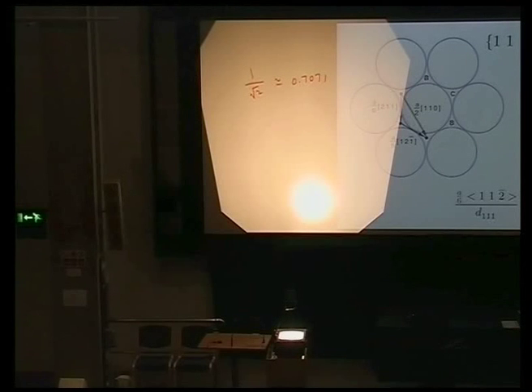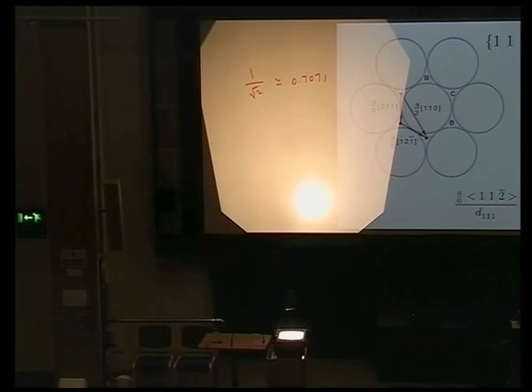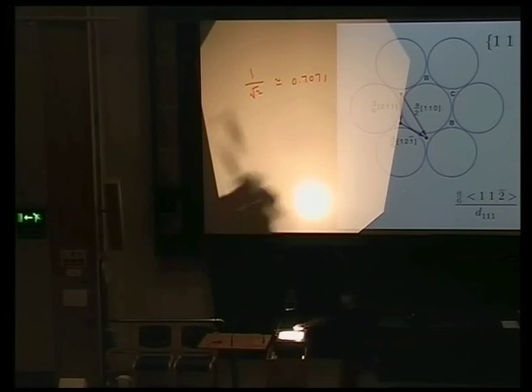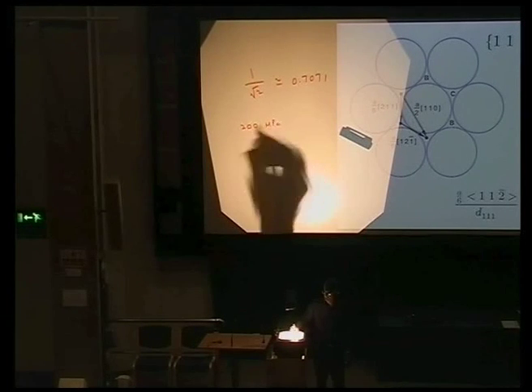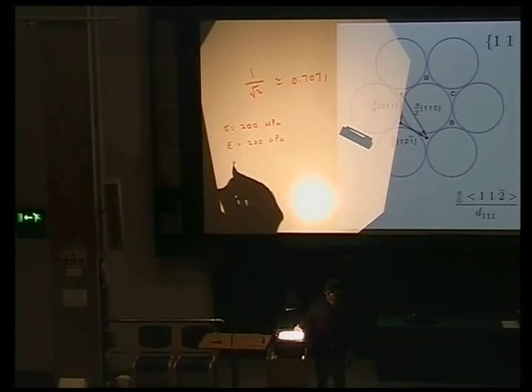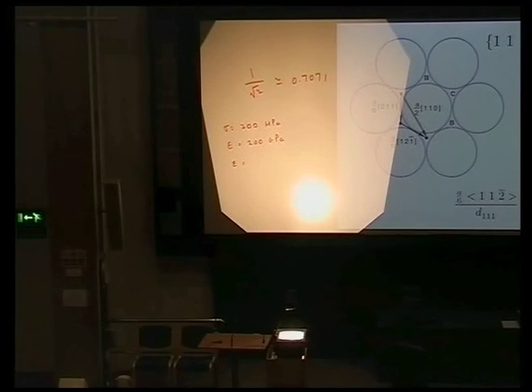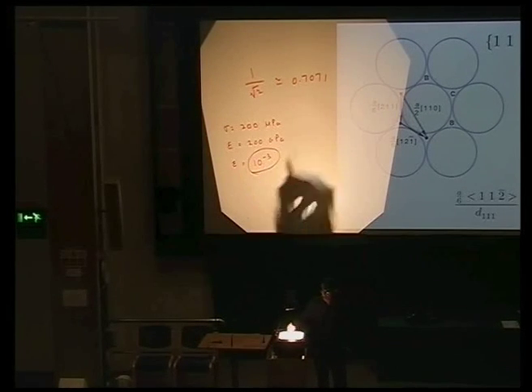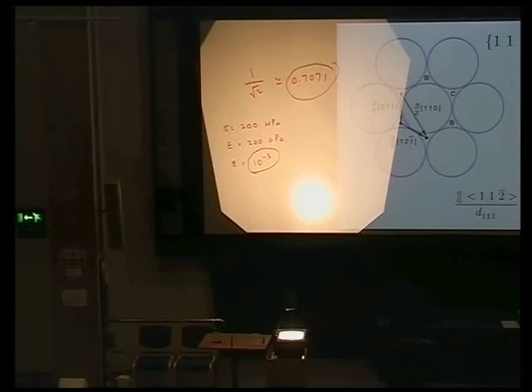To give you an idea of how large that shear is: if I have a modulus of 200 gigapascals and a stress of 200 megapascals, the magnitude of the elastic strain is 10⁻³. So this is a typical elastic strain, and 1/√2 ≈ 0.707 is the twinning shear — that's a massive shear. It will cause a lot of strain energy when it happens inside a constrained system.